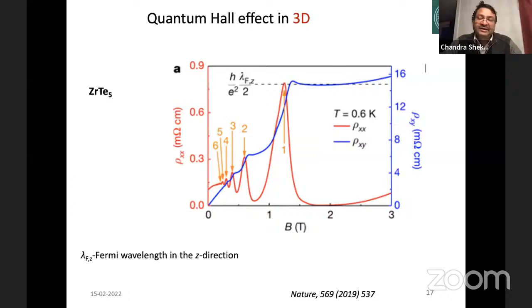But in a two-dimensional system, it is very easy: only e squared by h or h by e squared, depending on whether we are measuring resistivity or conductivity. Resistivity is some sort of inverse of conductivity. In resistivity we have h by e squared; in conductivity we have e squared by h, just the inverse of this value. But in three dimensions, it is not easy to quantize, and we are still looking at many more materials to achieve perfect quantization in a three-dimensional system.